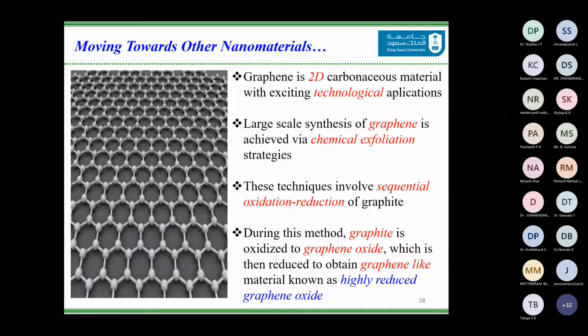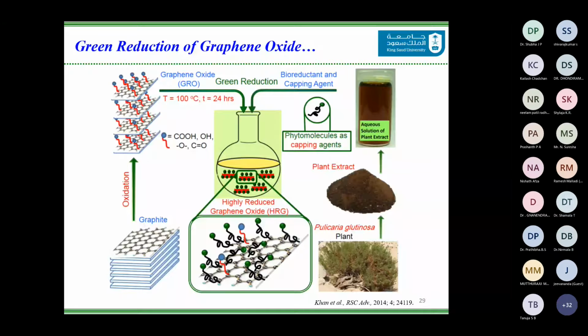So these separate sheets of graphene are usually termed highly reduced graphene oxide. And how is it done? First you take graphite and you chemically exfoliate it using KMnO4 and hydrogen peroxide. And as you can see in this structure, the sheets have separated. This separation of sheets gives us enhanced surface area to deposit any metal of our choice.